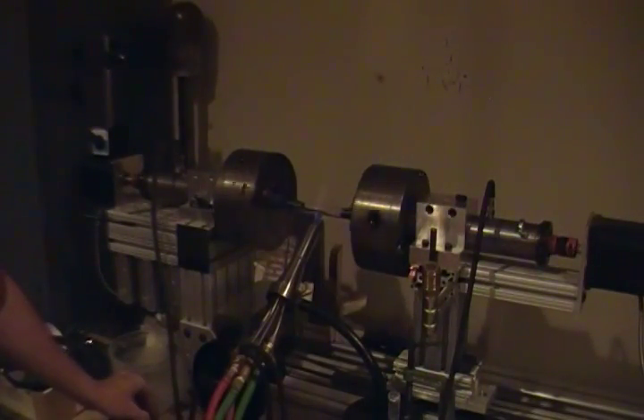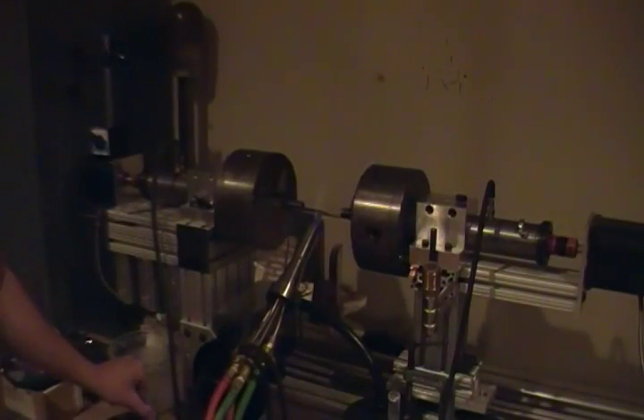Anyway, we got the torch on. We're doing a little bit of soak. Silica has basically almost no appreciable thermal expansion coefficient so you can really just go right in with the flame, not have to worry about thermal shock. But as a good practice to get good results, I like to have the parts hot and warm anyway just because you get a little bit better results.